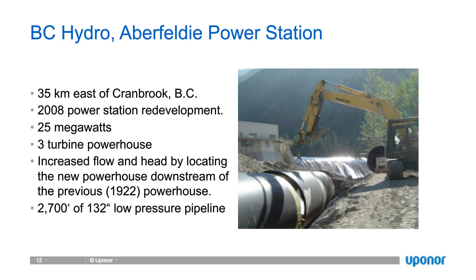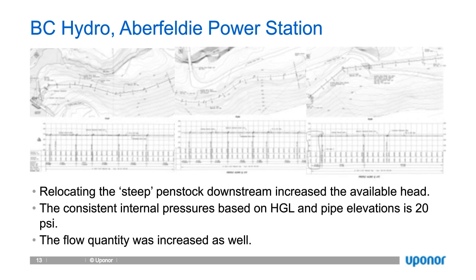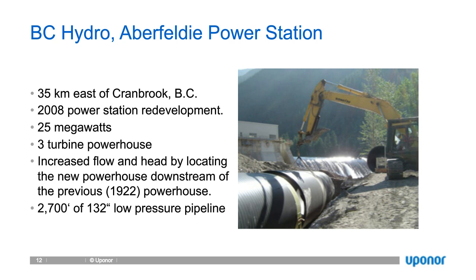And the reconstruction involved increasing the flow and the head, and that was essentially achieved by moving the powerhouse downstream from the previous powerhouse, which was right at the dam. We moved it down about 3 kilometers. And most of that distance was about 2,700 feet of 132-inch low-pressure Weholite pipeline. I'm going to just flip back for one moment. It indicated that there's increased flow.